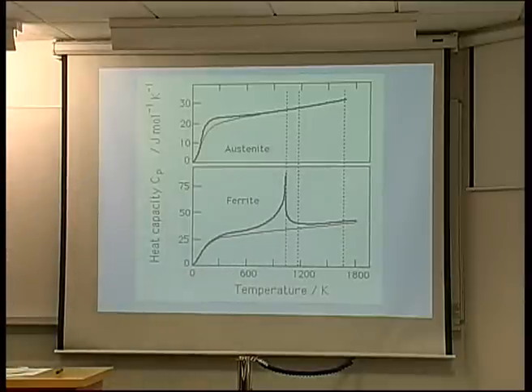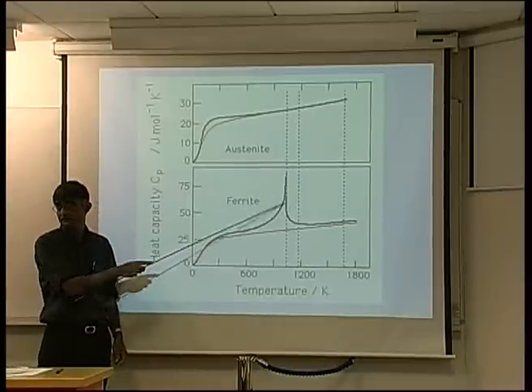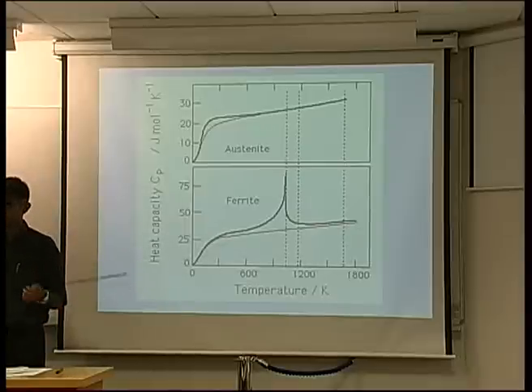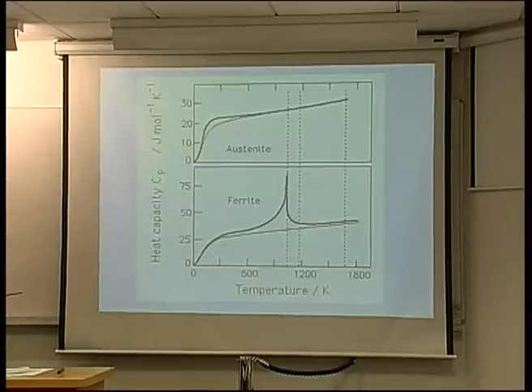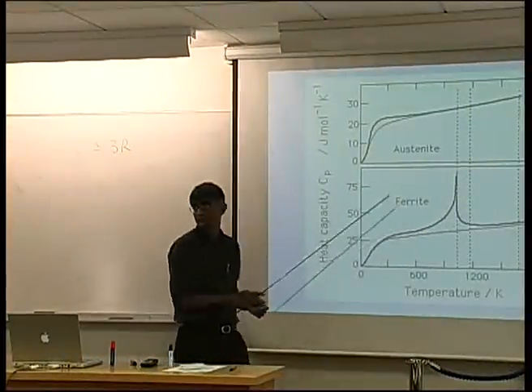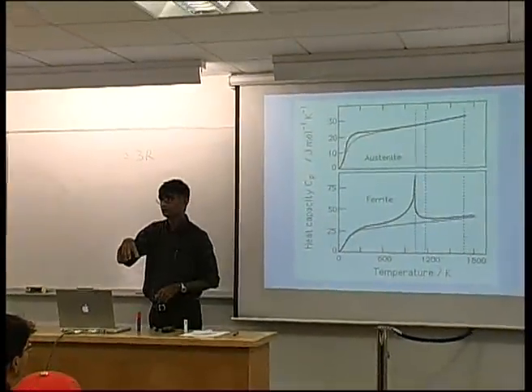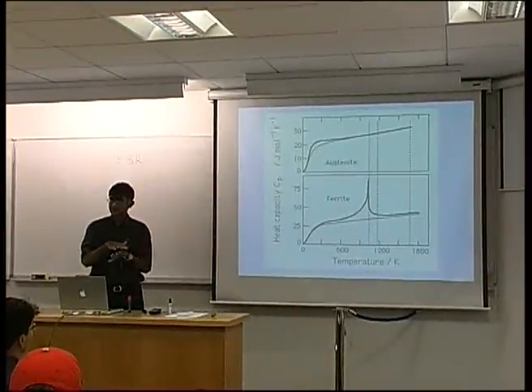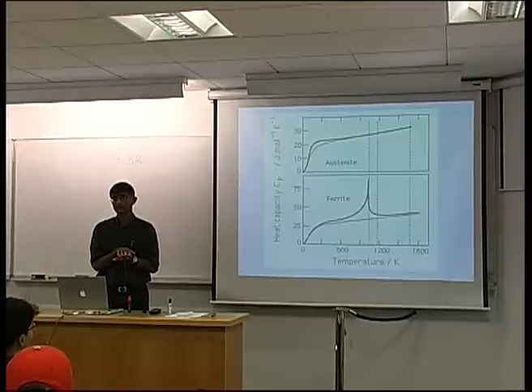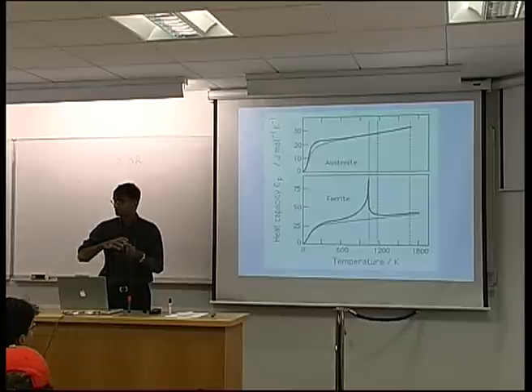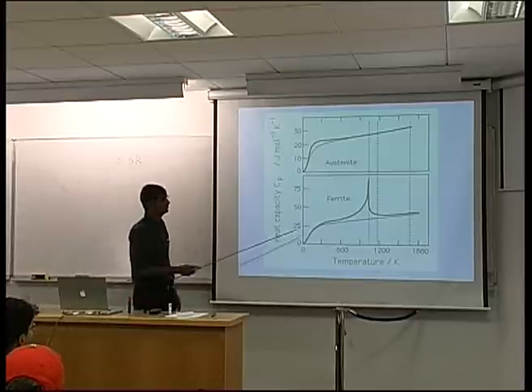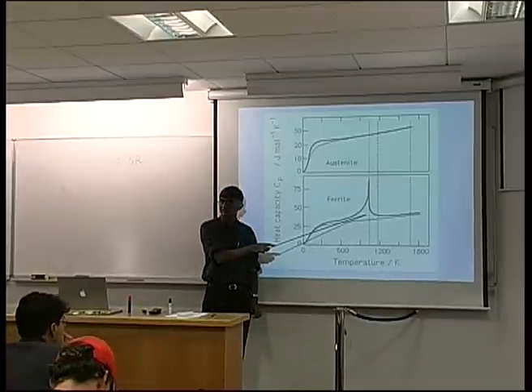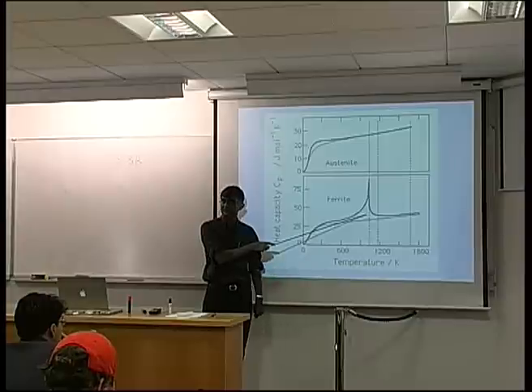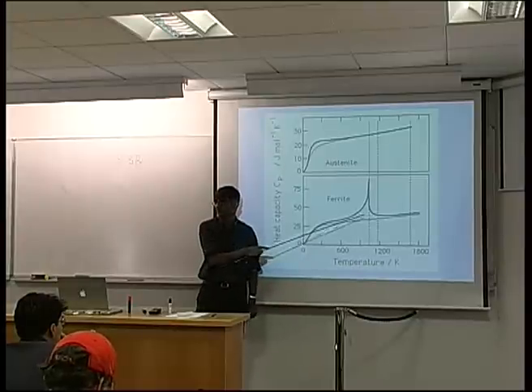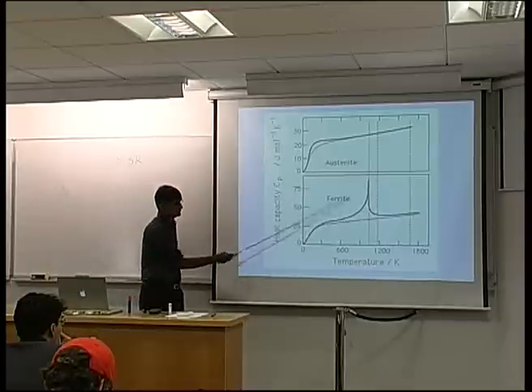In fact, body-centered cubic iron would not exist at room temperature if it weren't for this magnetic component of the heat capacity. You would not have a billion tons of steel produced every year if it wasn't for this magnetic component. We would have another form of iron, which is hexagonal close packed. And hexagonal materials are very poor in their mechanical properties because they don't have many slip systems. They can't deform very easily, so they behave in a brittle way. So we owe magnetism here a lot. Just imagine if you removed all the steel from your life, you'd be in big trouble. So this actually is a very, very large effect.